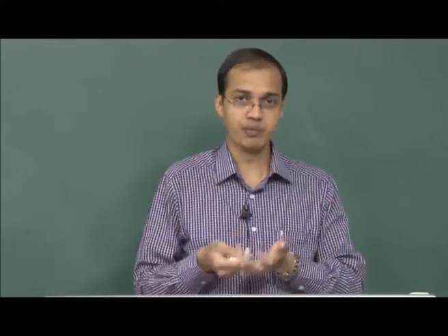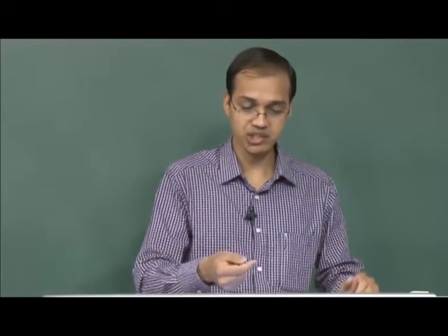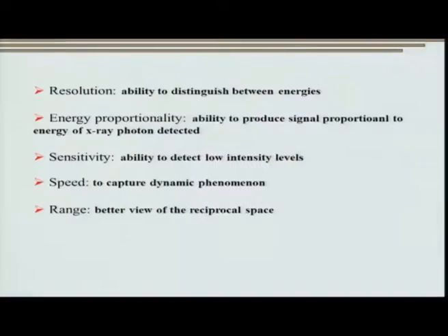Having said that, for the choice of a particular detector, we need to focus on the resolution, which is essentially the ability to distinguish between two energies. At the same time, what is more important is the energy proportionality, which is the ability to produce a signal proportional to the exact energy of the X-ray photon. Another important parameter is the sensitivity, which ensures that we can detect low intensity levels.